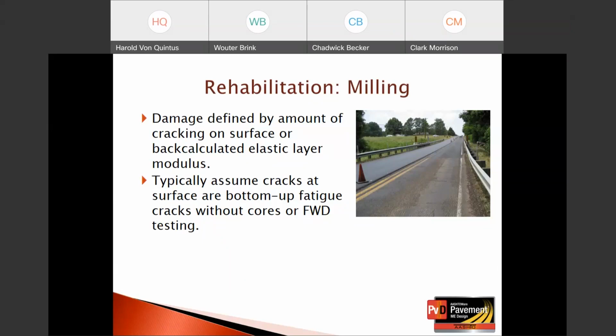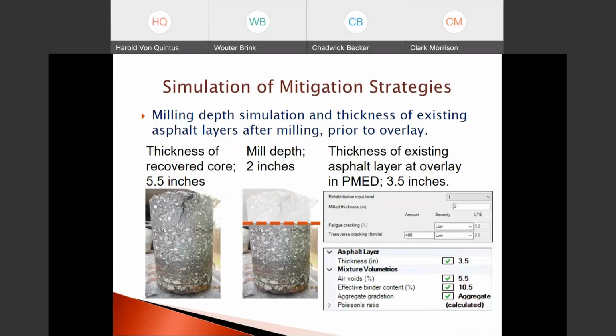Since they're assumed to be bottom-up cracks, any cracks we see at the surface, even though we're milling 1, 2, or 3 inches, that same amount of cracks, since they're bottom up from the bottom to the surface, will exist regardless of the amount of milling depth for a specific design strategy. If we don't have cores, then we don't have FWD testing to evaluate crack depth or to look at cracking at the surface with different potential mill depths. So that is one suggestion, that if we're doing rehab input level 2, the cracks at the surface, if we're doing milling, those would also be entered for the amount of fatigue cracking for rehab input level 2.